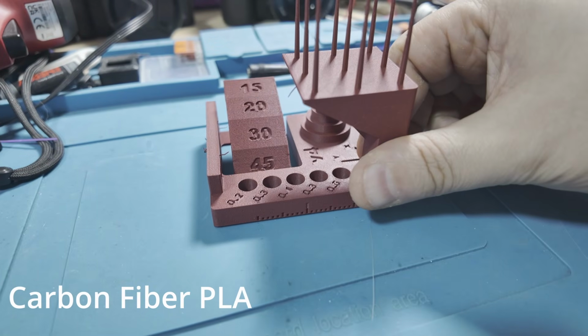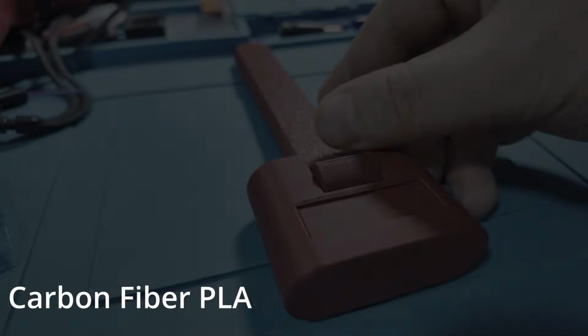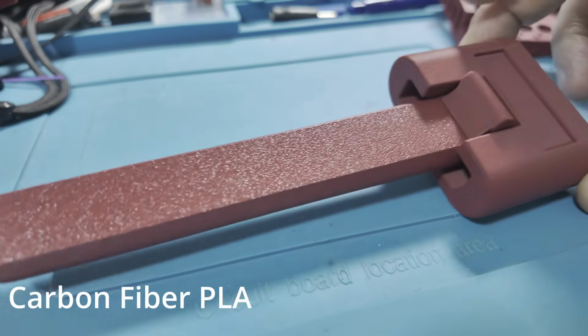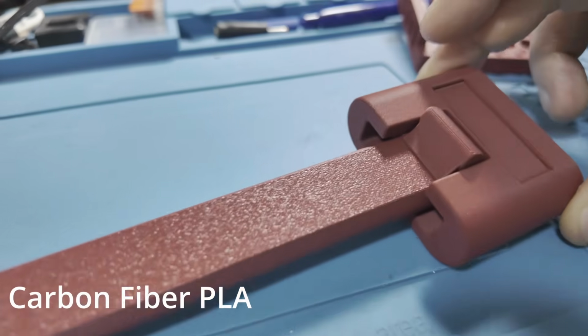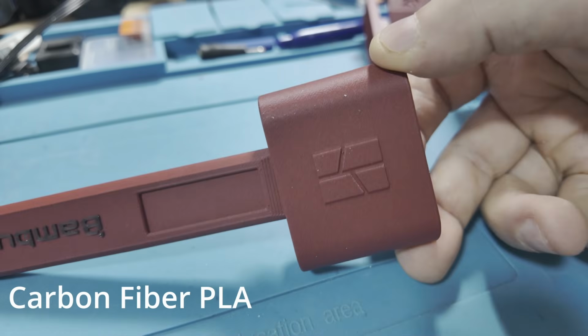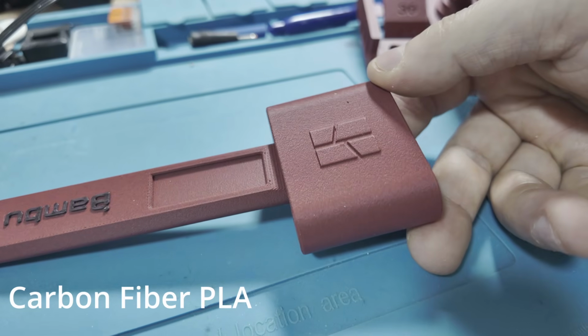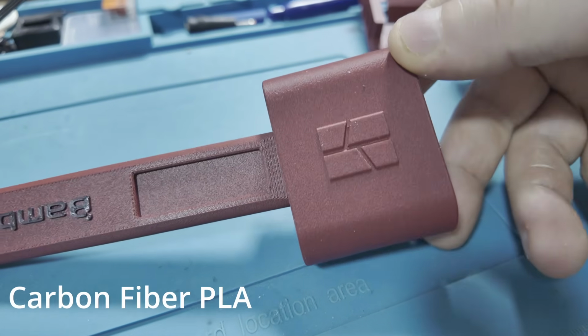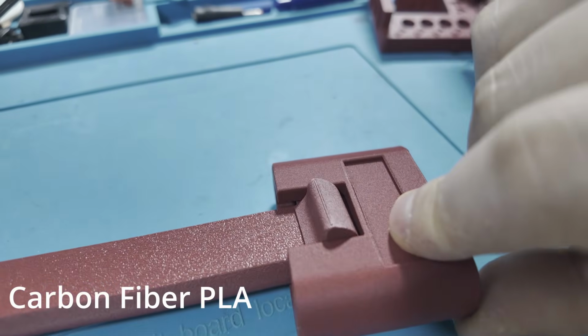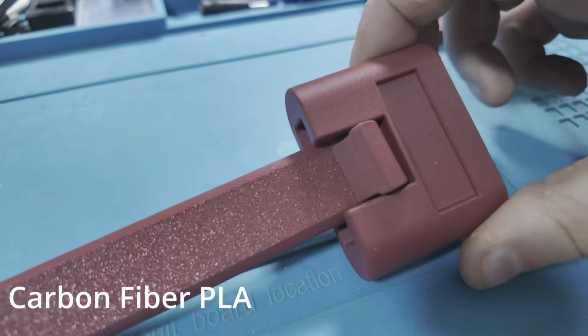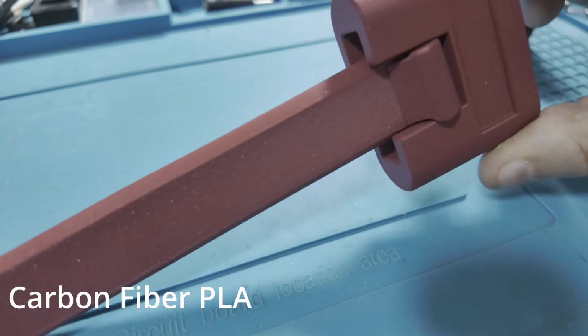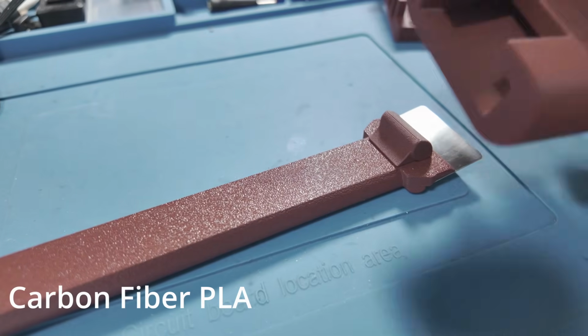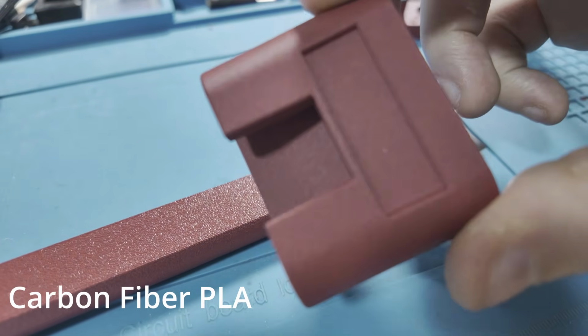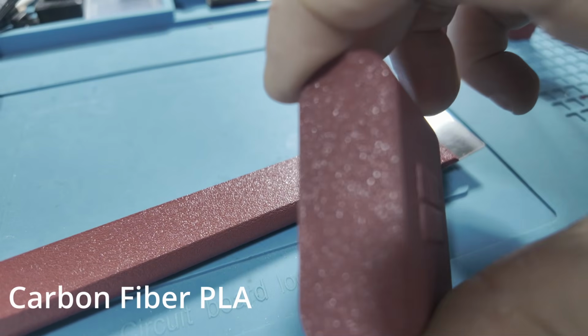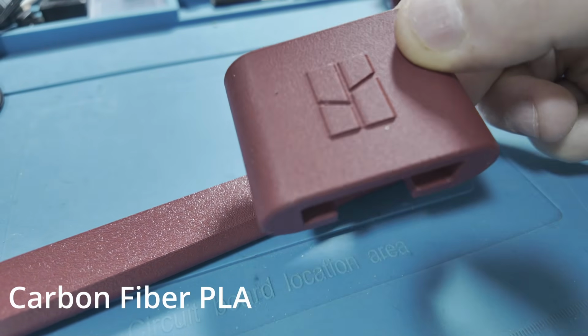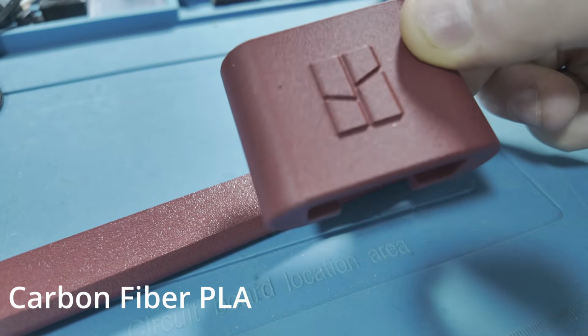This is exactly the kind of material where a diamond nozzle makes sense, because instead of performance slowly degrading, you should get the same results over time. The hidden benefit: with standard nozzles, wear changes your results. Tuning becomes inconsistent, prints slowly drift in quality. With diamond, that variable is basically removed. Especially with abrasive materials, metal-filled PLA, PLA carbon fiber, you get repeatable, stable performance. And for functional parts, that's huge.